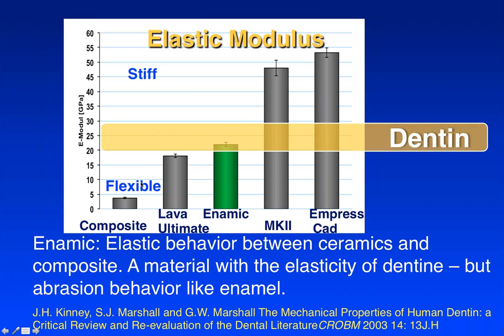As you go to the composite resin side, they're too flexible. As you go to pure ceramics, they start to become too stiff. And again, this was an item of very heated discussion among all of us in the development team about where we should be shooting for. Eventually, we all agreed that we should be in the dentin modulus area. If we start to get too much above that, then we get to something that's too stiff. And again, we have problems with the ceramic. The interesting thing about this material is that by adjusting the ceramic network, you can adjust the properties.